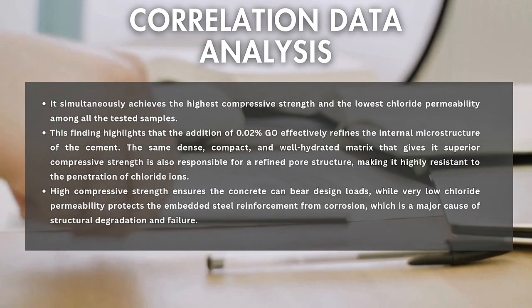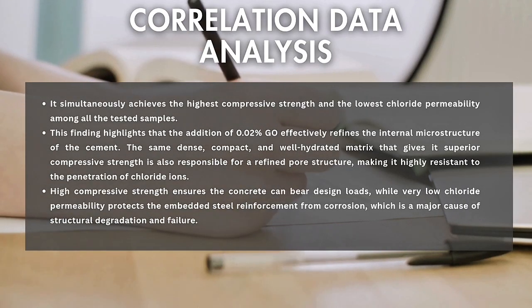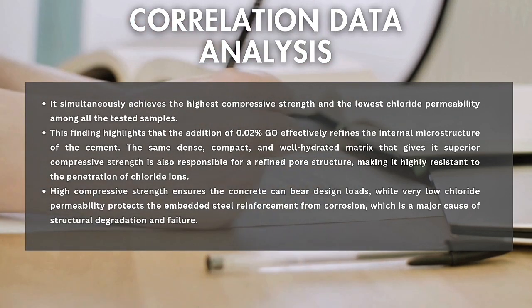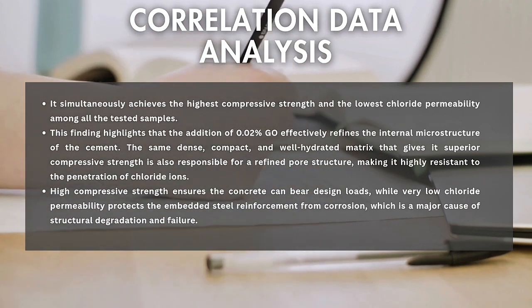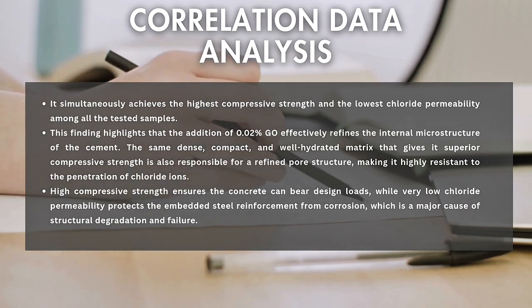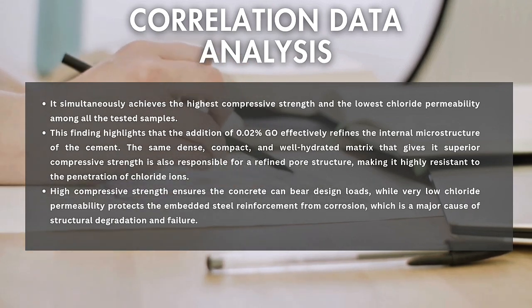This finding highlights that the addition of 0.02% GO effectively refines the internal microstructure and gives a superior compressive strength. It is also responsible for a refined pore structure, making it highly resistant to the penetration of chloride ions.